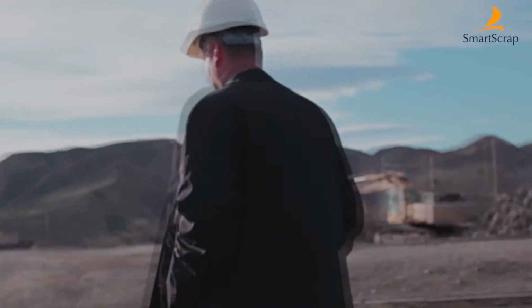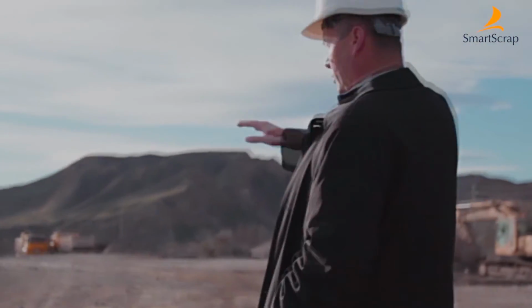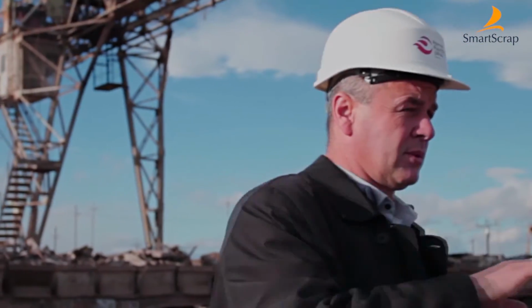The 16 to 60 fraction also wasn't any good. The content had a negative effect on the chemical composition of the steel we produce, which is why it was also a big question that we had to think through. We decided to run a complete modernization of the slag processing unit. The whole system has undergone a fundamental change. We chose the most suitable way and recognized the method of fraction separation and peeling.